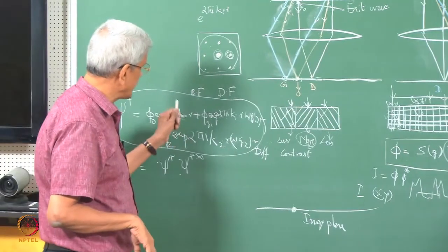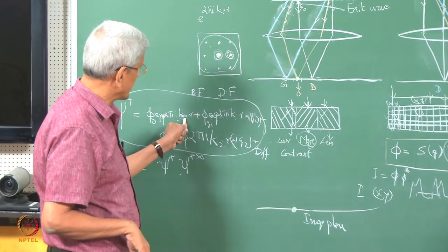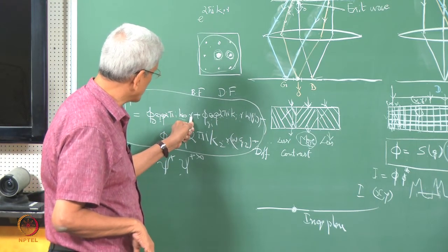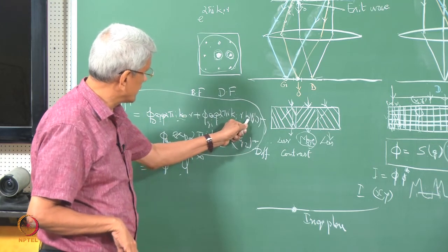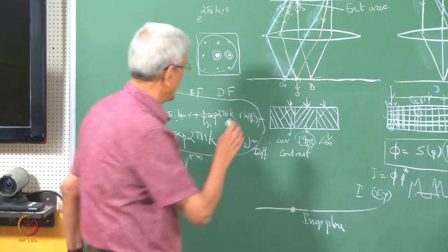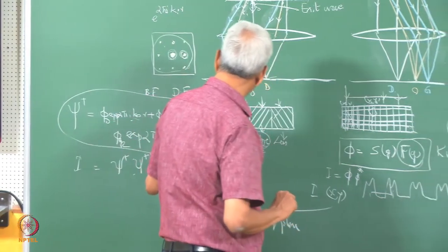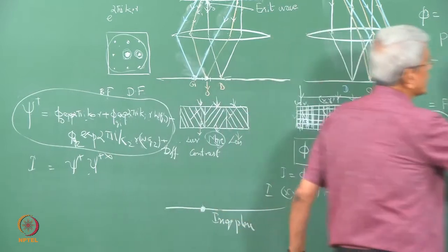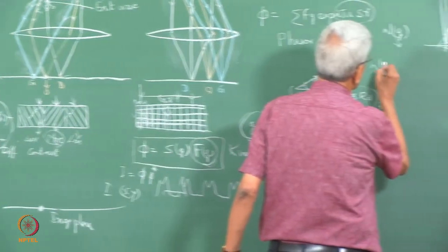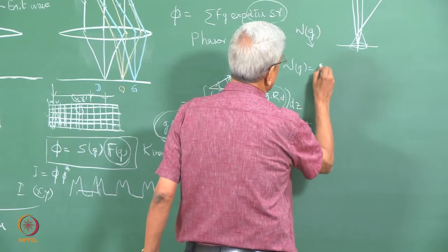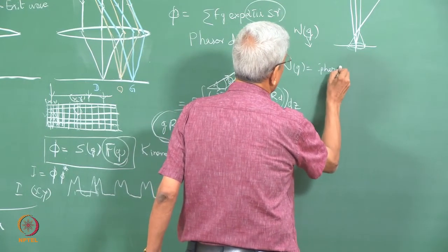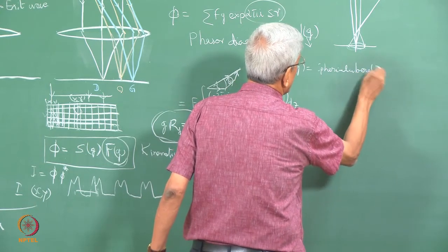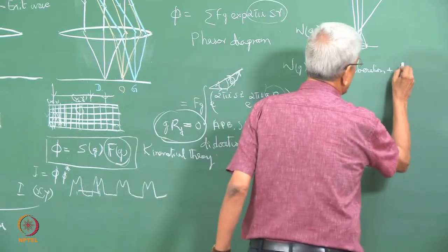So, this is exactly what is being done in a high resolution microscope: choosing specific values for the defocus, because if we consider this Wg, the effect comes from spherical aberration plus defocus.